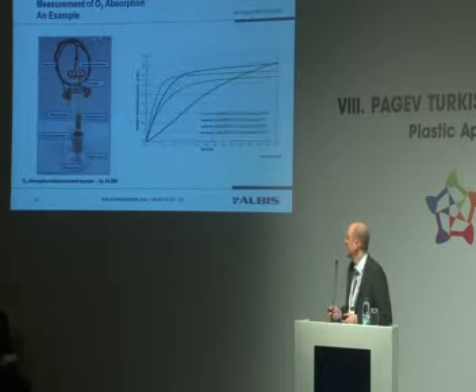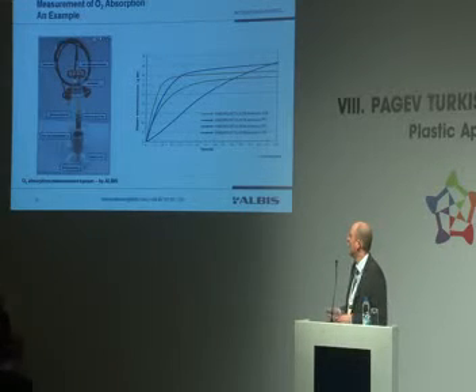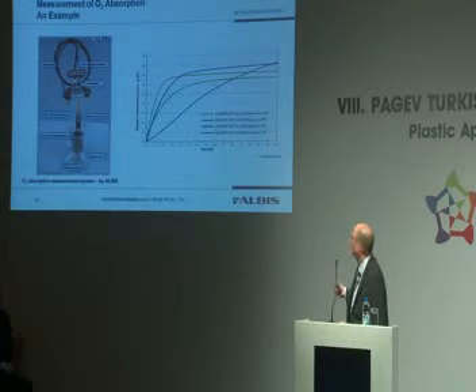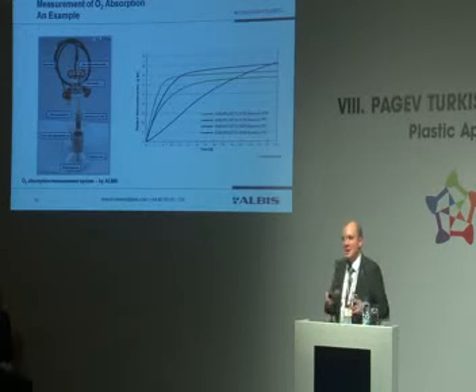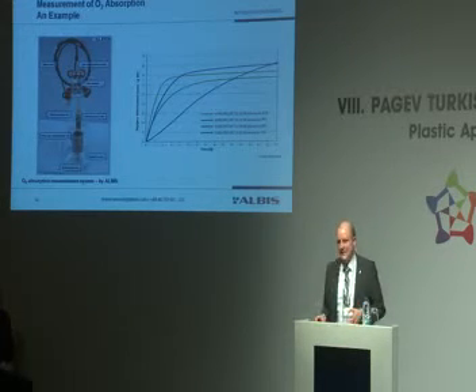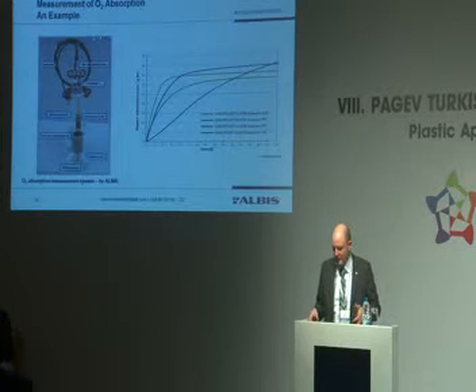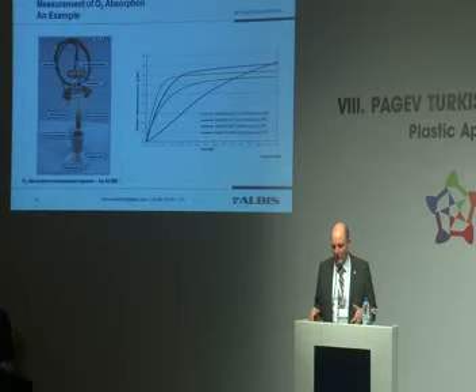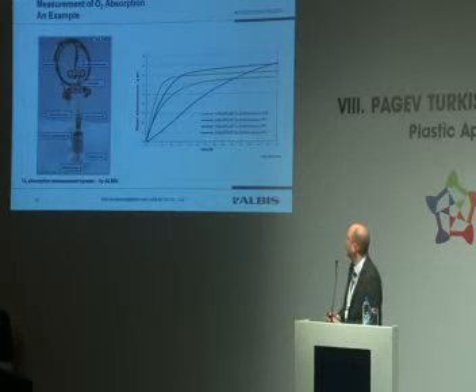So, with this device, we can get such a curve, where you can see on the y-axis the oxygen absorption of this sample in cubic centimeter oxygen per gram of used oxygen scavenger versus the time. And the different curves you see are the different products available on the market. So the basic difference between the products is the carrier material used. These days we can commercially offer EVA, PP, and PE, while polyamide is still a development grade, not yet 100% ready to market.